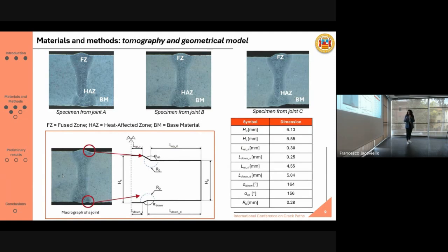Now here we have the micrographs that were obtained through computed tomography for the 3 specimens extracted from the 3 joints, A, B, and C. We are able to highlight the fusion zone, the heat-affected zone, and the base material. And we can see how, for example, for the specimen from joint C, there is a clear misalignment between the plates of the joint.